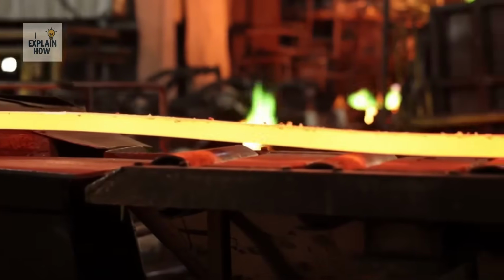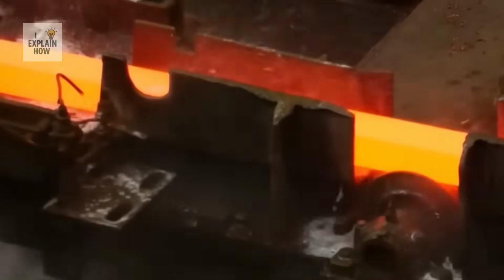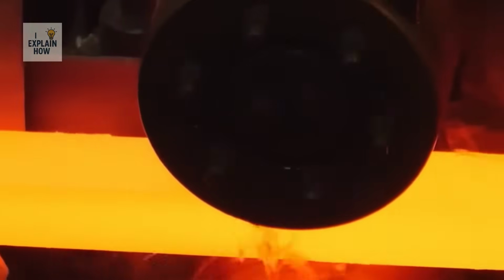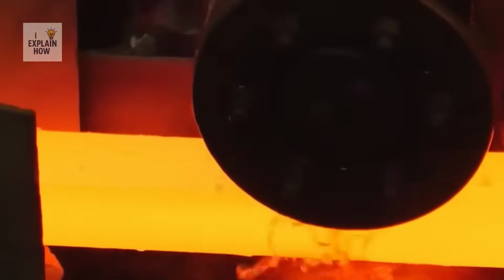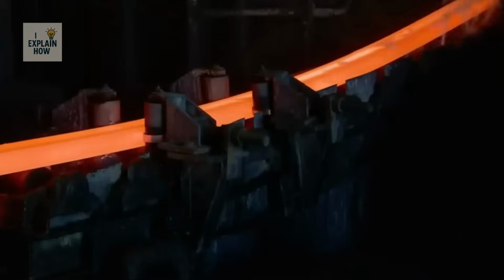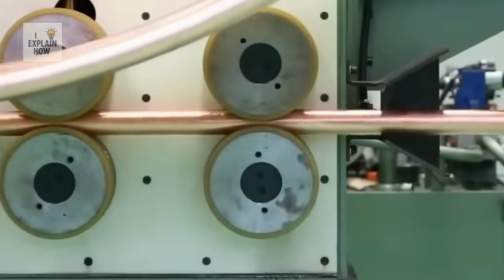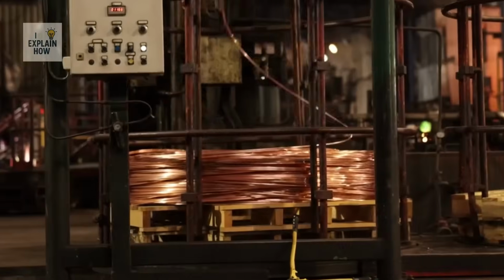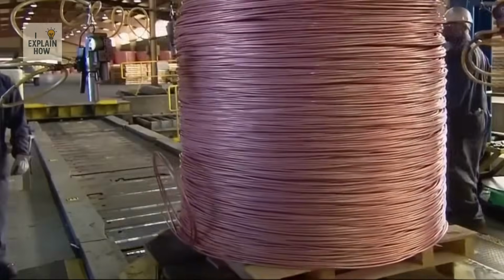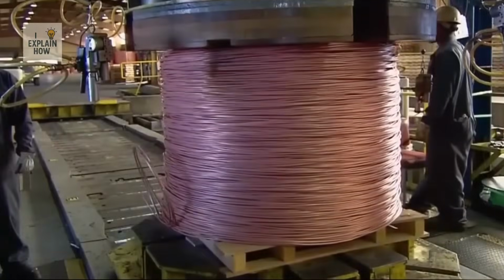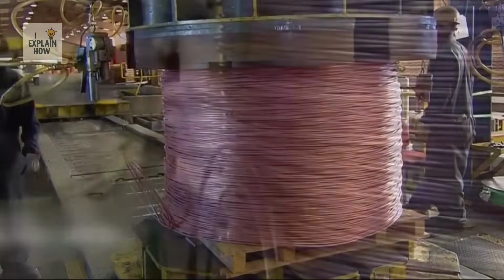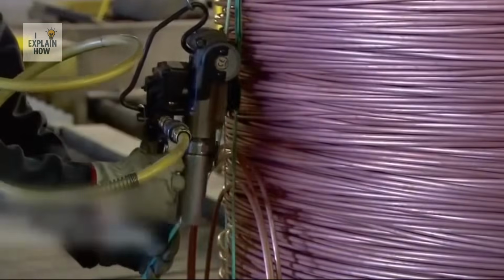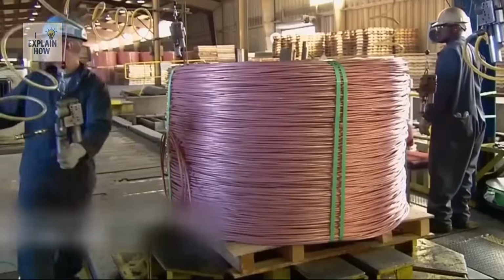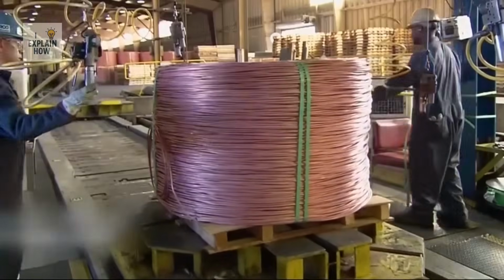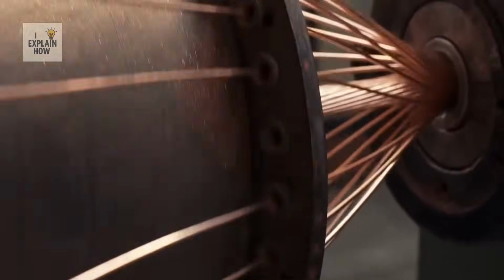The refined copper is then introduced into a vertical furnace where it is remelted. The molten metal is directed into a mold that produces large rectangular blocks approximately 6 m long. Upon exiting the mold, the copper is cooled by jets of water and takes the form of a continuous bar. This bar then passes between several rollers that reduce its diameter. At the exit, it is transformed into a copper wire approximately 7 millimeters thick.